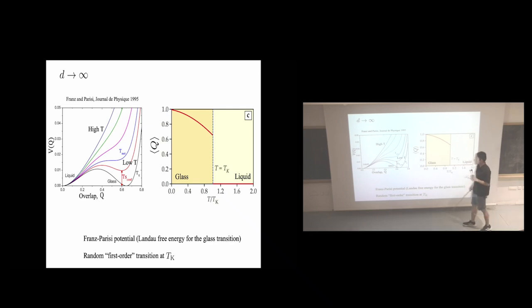Okay. So I have two more comments. The first: the temperature below which this metastable state appears is the mode coupling dynamical transition temperature. And also this height, basically the free energy difference between the liquid and the glass state, corresponds to T times the configurational entropy. Okay. This is nice.